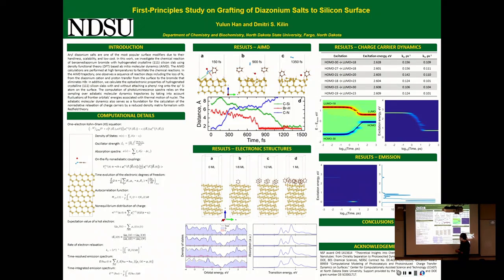So basically, we find the top three are very similar, which means the functionalization has minimum effect. But for the final figure, we can clearly see the decrease of the band gap. This is because for the HOMO, the carbon ring introduced a new state. Because the phenyl ring is kind of large and bulky, there is some pi-stacking or some reconstruction of the surface.